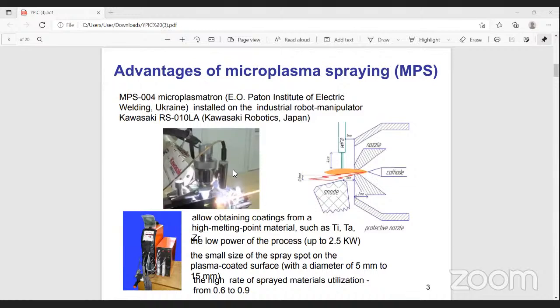Currently, thermal spraying methods are widely used in the metalworking industry, but for the biomedical field, it is an innovative issue with a potential that is currently being studied. One of the factors that prevent the introduction of thermal plasma spraying technologies in the production of biocompatible coatings is a possible heating of the implant during the process of coating deposition with a jet of high temperature plasma, which can lead to changes in its shape and mechanical properties. The use of microplasma spraying technology allows avoiding volumetric heating of the implant due to the low power of the process, up to 2.5 kilowatts.